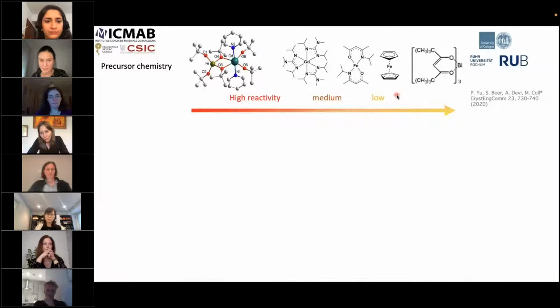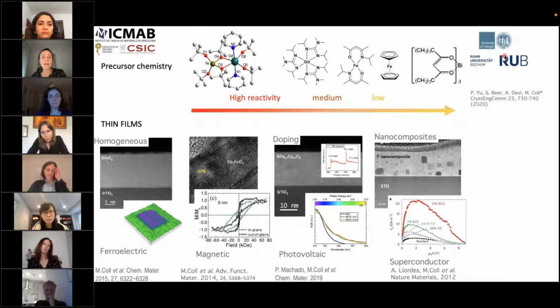So among the bunch of complexes that we investigated in collaboration with the University of Bochum, I selected 4 systems to present you here. And they are thin film systems. I will start with the Bismuth Ferrite, which is a multiferroic material. We've been able to obtain really nice, highly epitaxial film, meaning that we have a preferred orientation, which strongly determines the properties.